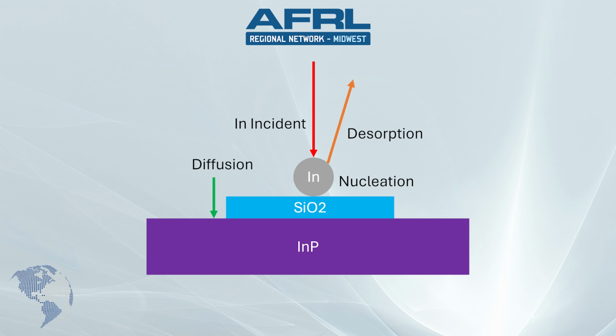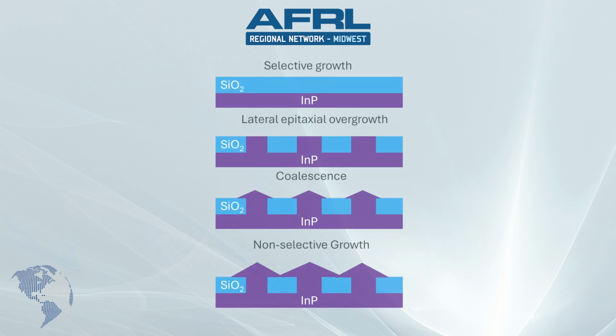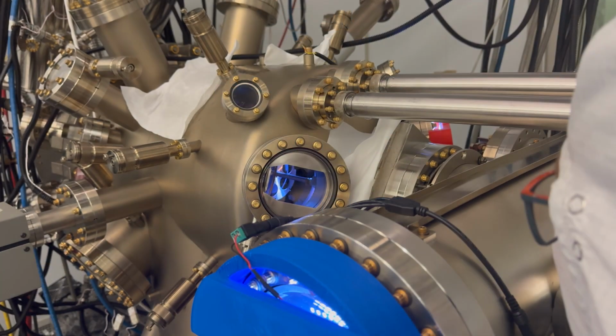Now, normally we grow on perfectly crystalline, atomically smooth III-V wafer surfaces. So the challenge here lies in growing on top of patterned SiO2 photonic crystals. The SiO2 is amorphous, so it is critical to avoid deposition on those regions in order to prevent random polycrystalline growth. So the secret sauce lies in a process called selective growth, where the III-V material only deposits on the wafer surface and ultimately buries the low index photonic crystal in high index single crystal semiconductor material.